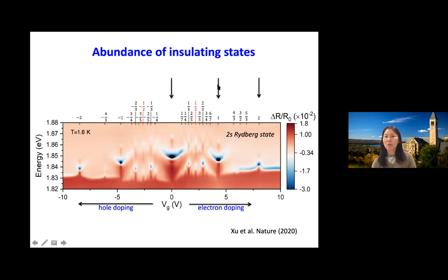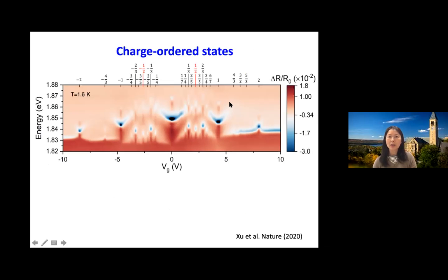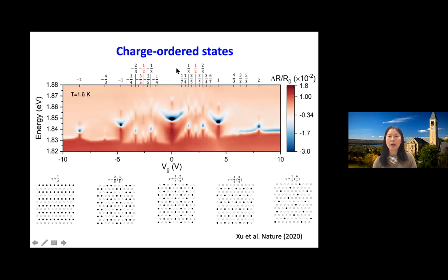This one is the Mott gap we've discussed, and that's the first Moire mini band gap. You can also see this on the hole doping side, so that looks like a whole Moire band. And then in between, you see a bunch of those fractional filling states. We were able to match them extremely well with the predicted ones from the extended Hubbard model.